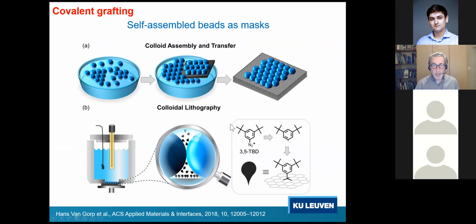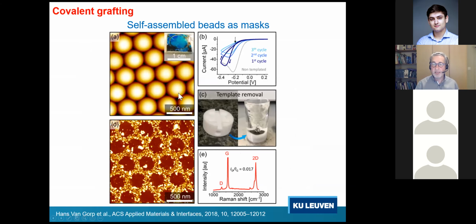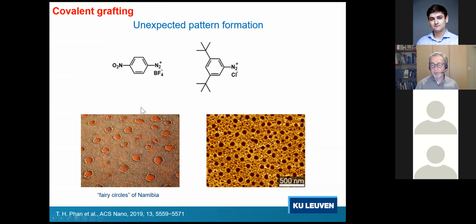We can also try to control at a bit higher scale, at the micro scale. One of the approaches that we took was to cover the substrate, not with molecules, but with beads that by themselves then formed a self-assembled network. So plastic beads, polystyrene beads. Here you see an AFM image of a layer of these beads on the surface. If we then expose this type of template to reacting molecules, we see that the molecules graft in between these beads. Well, this is a straightforward approach.